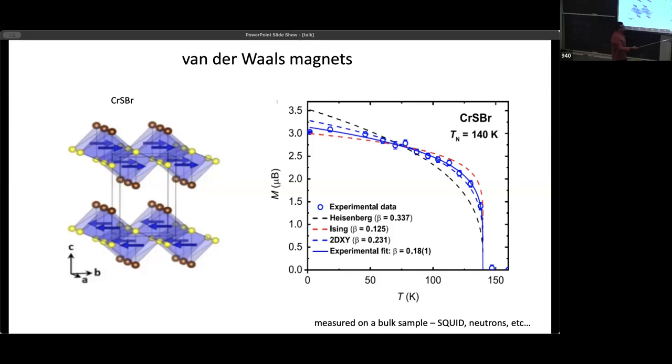And this is pretty plain vanilla in terms of magnetization. That's the magnetization as a function of temperature. And around 130, 135 Kelvin, it hits its Néel temperature, or Curie temperature, if you want to think of one layer. And then above that temperature, it's a paramagnet. So above that temperature, the spins are this way.